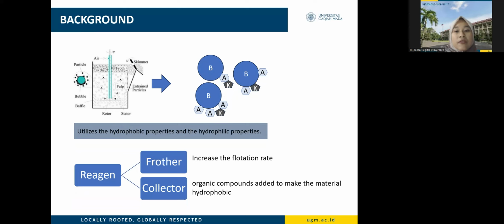The types of reagent in flotation are frother and collector. The frother in the flotation process functions to increase the flotation rate by reducing the surface tension of the bubble so that the bubbles formed are smaller and have a large surface area for particles to stick to. Collectors, which are organic compounds, are added to the process to make the selected material hydrophobic through an adsorption mechanism onto the surface of the selected mineral. One type of collector is kerosene, which is included in the non-ionic collector group.